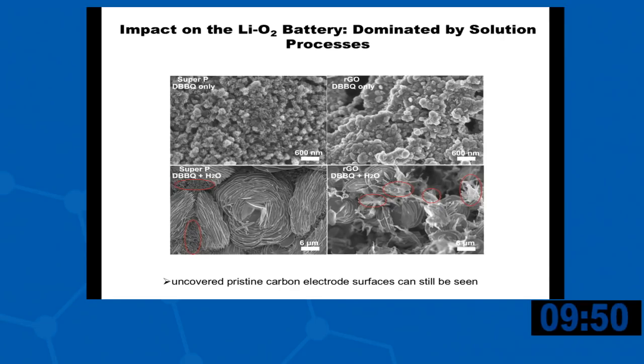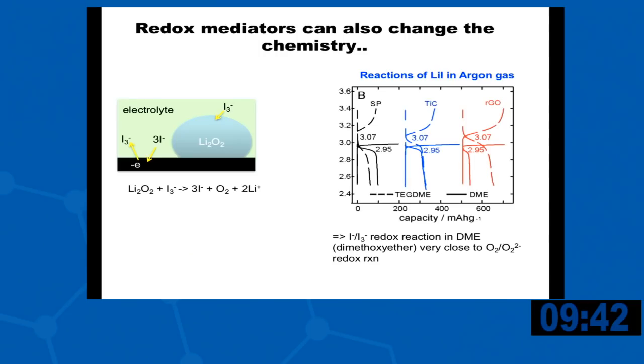So you could actually go further if you had more lithium source. So we're actually limited by how much lithium we had on the anode of our materials. And so the only thing I wanted to say was that redox mediators can also change the chemistry. This is our work previously looking at triiodide reactions. So you can use iodides as redox mediators. Iodides going backwards before was between iodide and triiodide, and they are sitting at very much the same voltage as the lithium, the oxygen reaction.